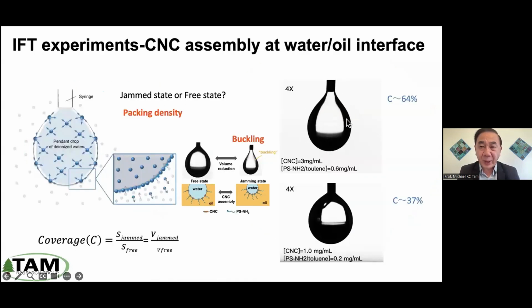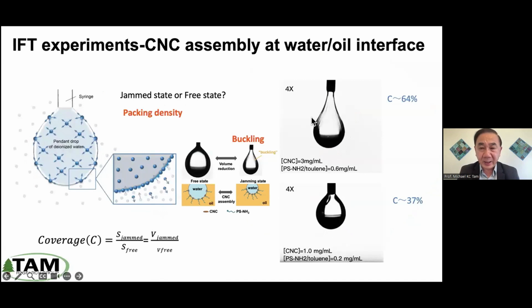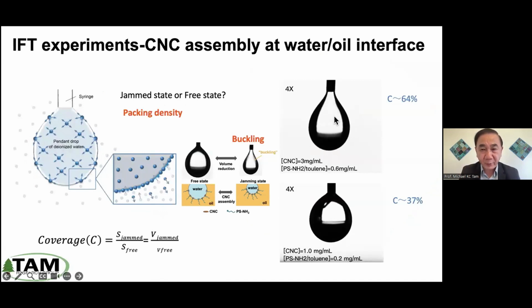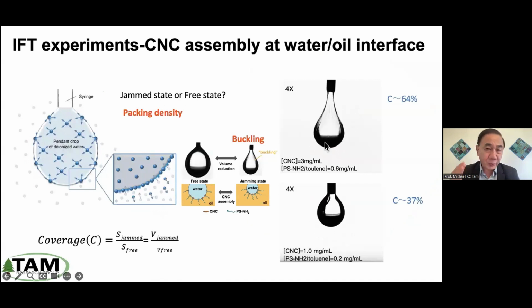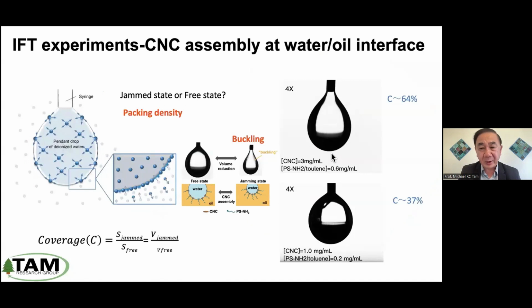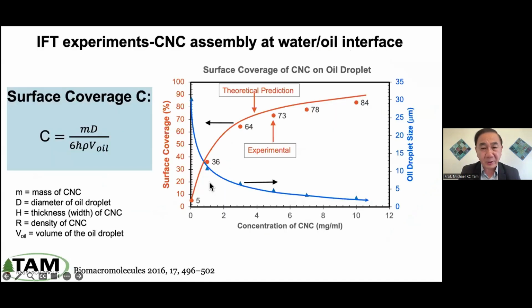So we try to look at the partitioning of the CNC to the interface, and if you suction and remove the water, we get this sparkling, demonstrating the surface now is saturated with CNC. And we can then do analysis, and we can look at the amount of CNC absorbed at the interface. And as more is absorbed, the particle size drops from 30 to 3 micron.